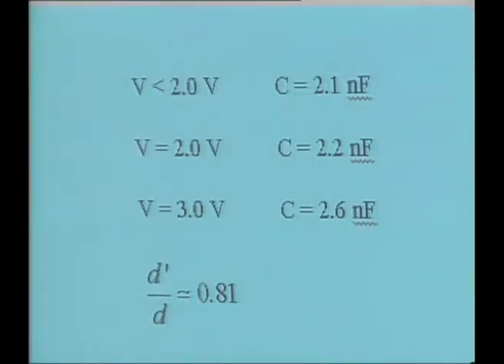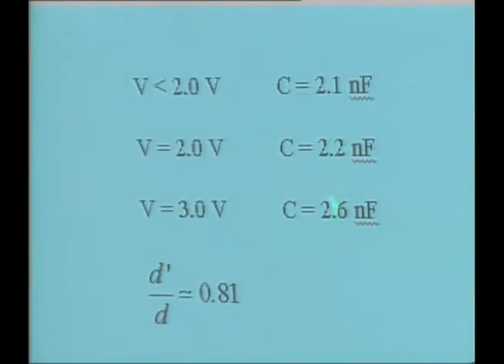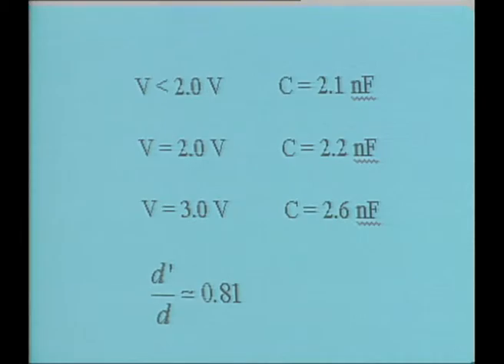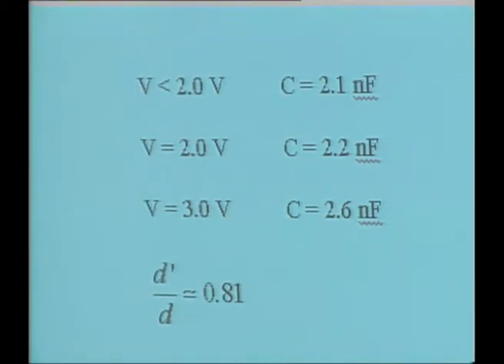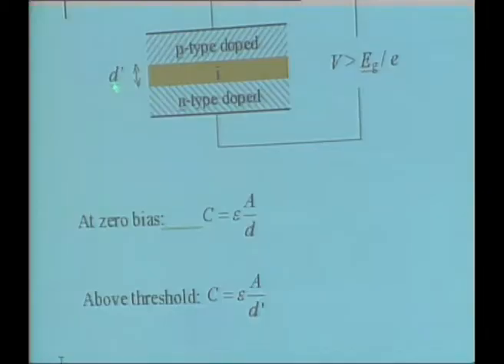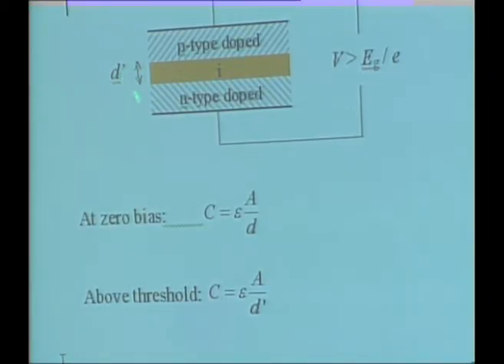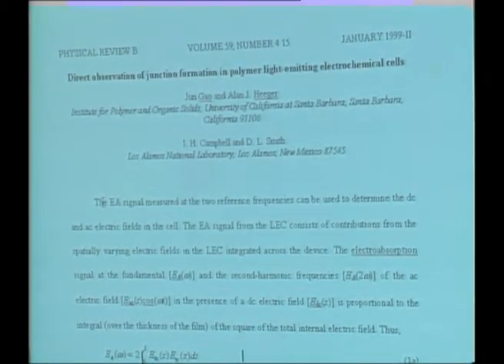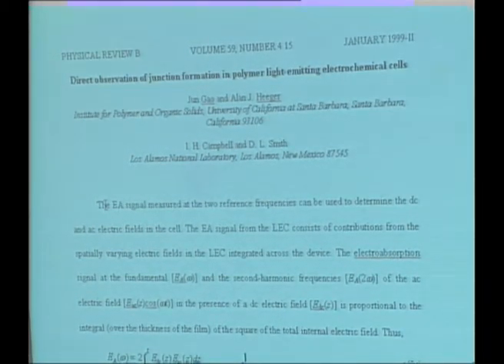Okay, the area hasn't changed. But now, this gives us a hint that the thickness of the device has changed, as suggested by this photograph, and that d prime is about 0.8 of the total thickness. This is a collaboration between our group and the Los Alamos group, where they were doing electroabsorption. Electroabsorption gives you a way to measure the internal field inside a device.